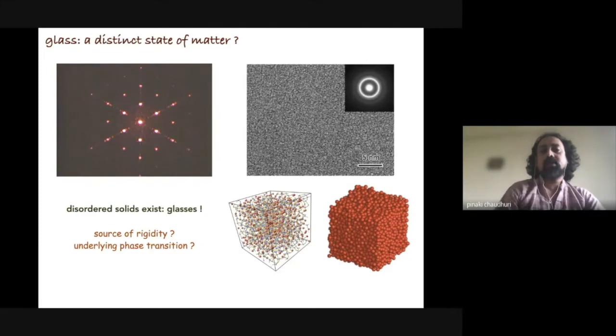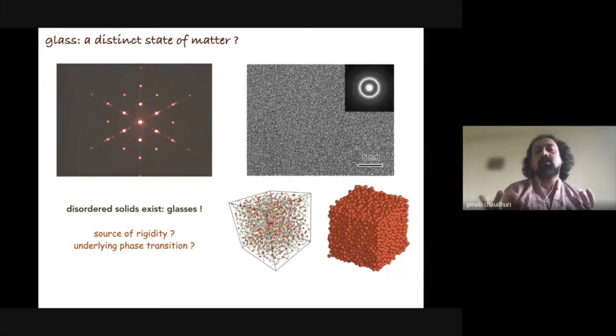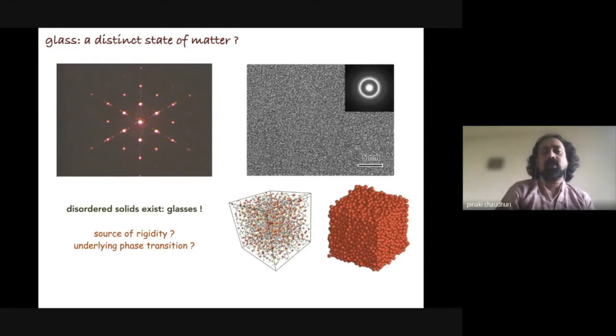On the right hand side, it's a metallic glass. If you do the same kind of experiments there, you can see that the pattern you get from this diffraction doesn't have any structure at all. There is no organization that you can see. So this is the contrast. You have in one case a solid which is crystalline, with an ordered structure, and on the other hand you have a glass which has a disordered structure.